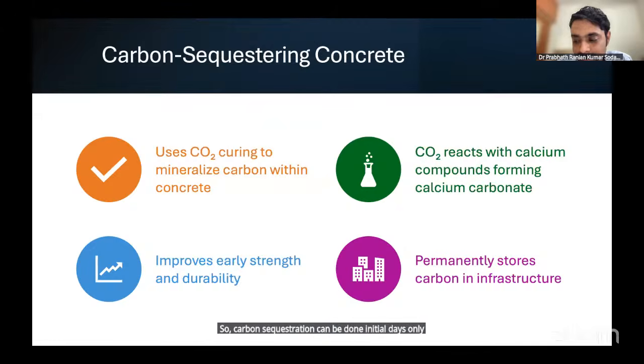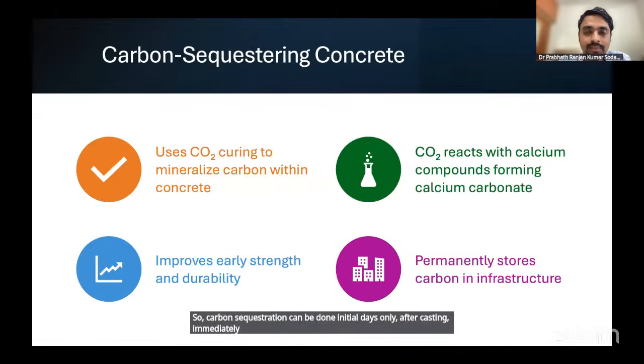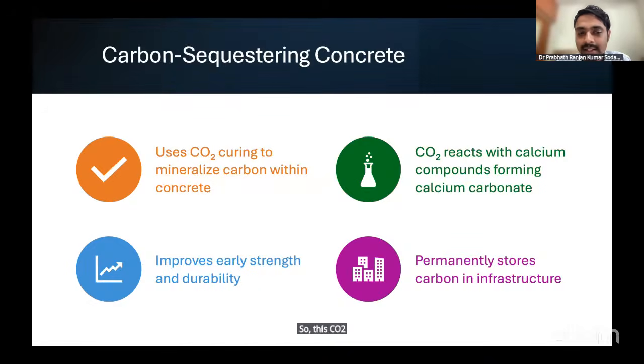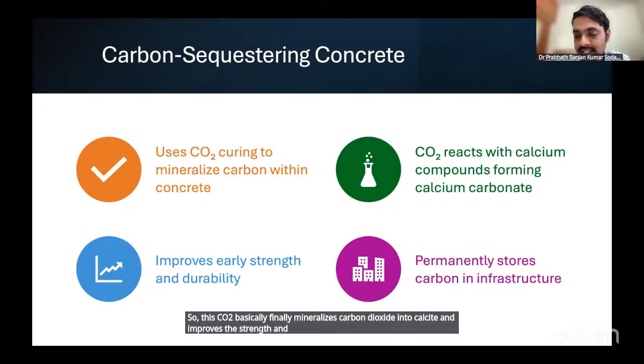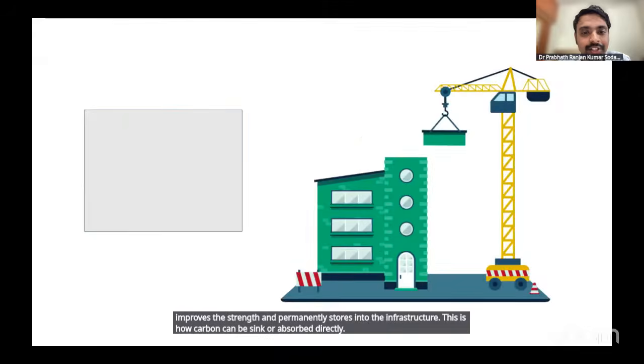After casting, we must expose it immediately, because that's when the maximum amount of calcium hydroxide is available for the reaction with CO2. So this CO2 basically mineralizes carbon dioxide into calcite, improves the strength, and permanently stores it in the infrastructure. This is how carbon can be sunk or absorbed, directly by reaction.